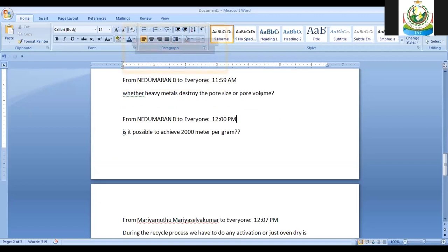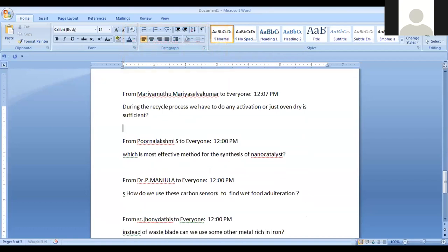Whether heavy metals destroy the pore size or pore volume, they have asked. It's not clear, the question itself. Is it possible to achieve 2000 meter square per gram? Yeah, I achieved 2500, nearly 3000. That report is not published. You may be going to publish it, because the condition is very critical. We need to avoid air during the carbonization and pre-treatment. So many pre-treatments are there. Finally we get a very small amount of carbon, but with high porosity. Our laboratory people are going to achieve large-scale synthesis of highly activated carbon with a high surface area. My best level is nearly 2,825 meters square per gram. So it did not reach 3,000. I tried my best.